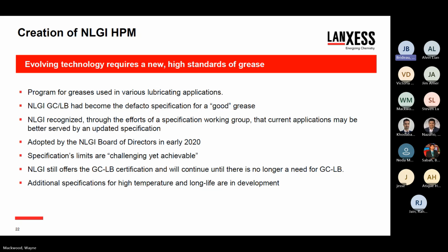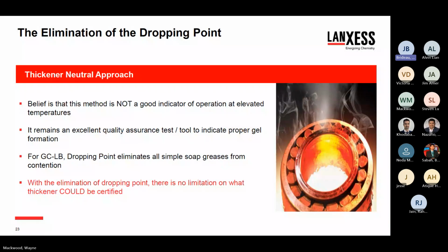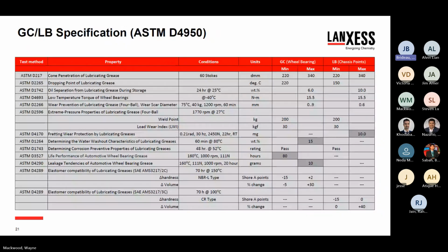The one thing that you're going to notice in the HPM spec that I'm about to present is that we have removed the dropping point. The one issue with the GC-LB, by including the dropping point as part of the specification, is that the dropping point is set at a minimum of 220°C for the wheel bearing grease. Well, lithium 12 grease will not meet 220°C. You have to move to a lithium complex, or a possibly heavily additized lithium grease might meet that 220. While the GC-LB does not state that specific thickeners can or can't be used, the dropping point immediately eliminates simple soaps. They're all gone, so they're not available.